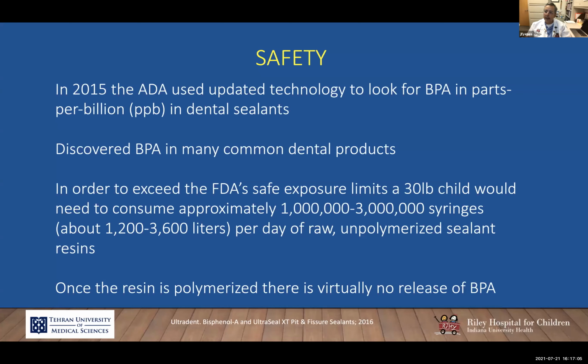We did one study here in Indiana last year, using a very interesting technology to measure the amount of BPA in parts per million in patients. We placed sealants in about 200 kids, and then we collected saliva samples over a 2-month period. We placed 4 sealants in all the first permanent molars, and we followed the kids with saliva samples every other day for over 2 months. And every sample, we processed to look for BPA, which took forever, a very expensive study. The conclusion: you can find some traces of BPA in the first 24 hours after you place the sealant, but in the subsequent samples, we couldn't find any BPA.